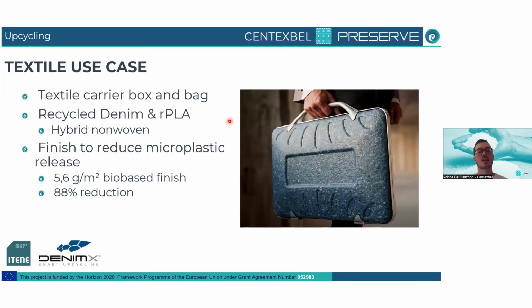Then the last slide I wanted to show is not something that is used with these fibrillated materials or the self-reinforced PLA material, but is actually just a recycled PLA material. This is done by multifilament extrusion, and then by creating a non-woven. This is a hybrid non-woven with Denim X. So this is a company also in the Preserve Consortium, and they use their denim fibers together with these RPLA fibers to create a hybrid non-woven.